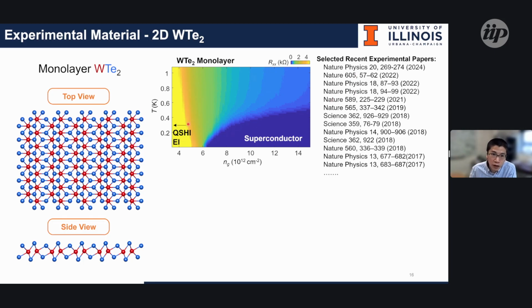This system was proposed and also observed as a quantum spin Hall insulator, and experimental studies revealed that it is a superconductor. So it's a tunable system where you can go to a topological phase as well as superconductivity. Later on, our work revealed that it is possibly an excitonic insulator in the monolayer quantum spin Hall insulator. And the structure of this system is a rectangular lattice.